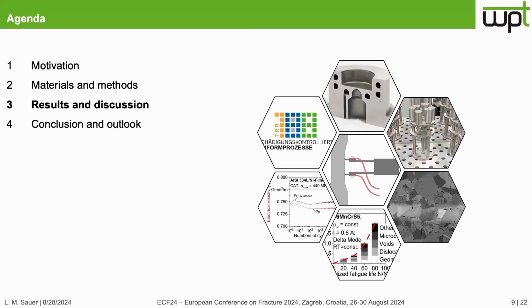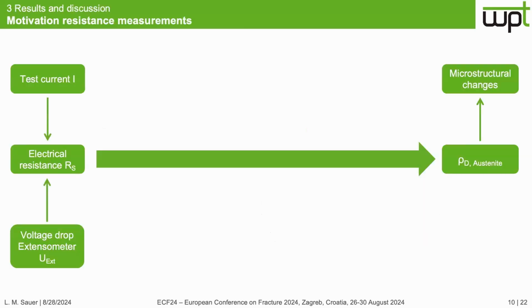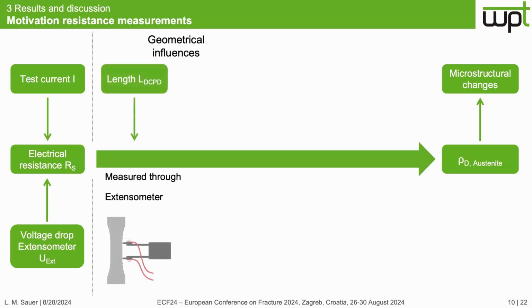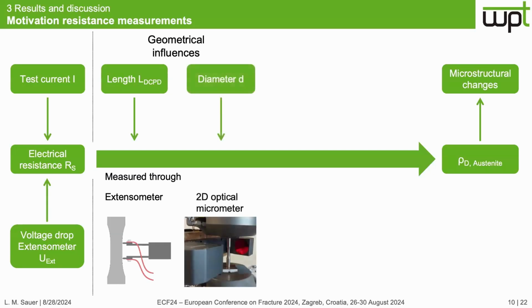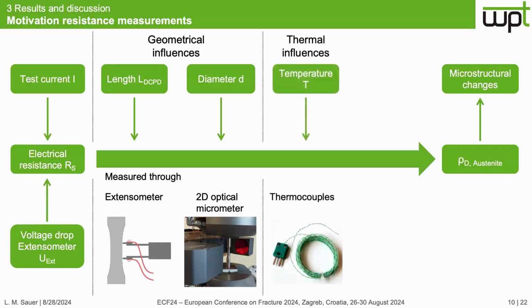And I will now come to the results and discussion. The idea of this work is to start with the electrical resistance, determined from the test current and the voltage drop at the extensometer, and then compensate various influence factors, beginning with the influence of the geometry, namely the length measured through the extensometer, and the diameter measured through a two-dimensional optical micrometer. And for the thermal influence on the electrical resistance, the temperature was measured with thermocouples.